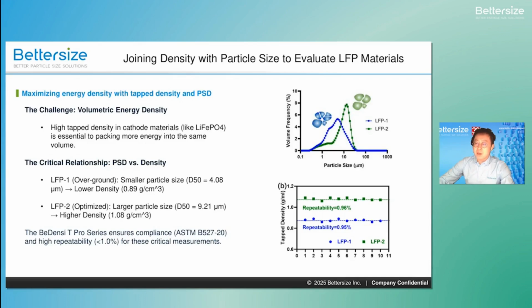Comparing these two samples, the LFP1, the blue curve, was overground to a fine 4 microns, yet it resulted in a lower density of 0.89 grams per cubic centimeter. Meanwhile, the optimized LFP2, the green curve, with a larger size of 9 microns, achieved a significantly higher density of 1.08 grams per cubic centimeter.